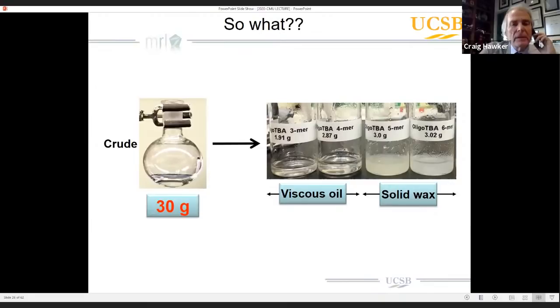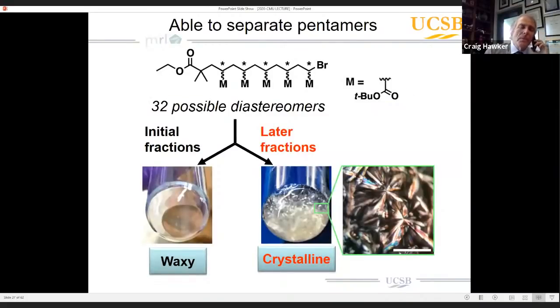But then surprisingly for us, these oligo-tert-butyl acrylates started to become waxy. And so then we looked into more detail in the pentamer. And what Jimmy and Alison were able to do was to re-purify that pentamer. So now we're looking at pure pentamer. The beginning fractions of pentamer, the ending fractions of pentamer, but we do still see a separation. And the initial fractions, as you can see here, are really waxy and, you know, not that much crystallinity to them at all. And the later fractions were very highly crystalline.